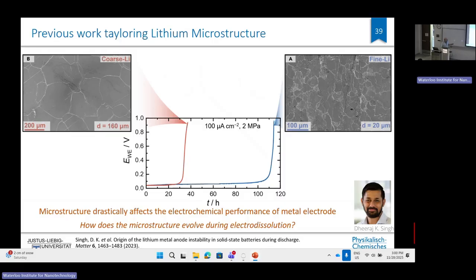But nevertheless, these white lines we thought may be grain boundaries, but the lithium has a passivation layer. It could also have been cracks in the passivation layer. So we were not sure whether we really see the microstructure. That's an important point. Nevertheless, the small-grained lithium in stripping delivered more charge than the large-grained lithium. So in principle, the assumption that small-grained lithium is better was okay.